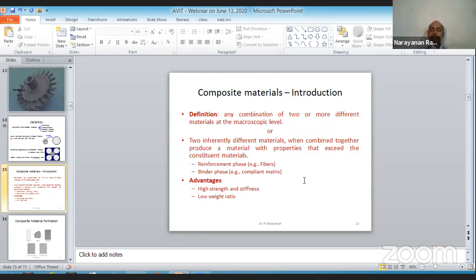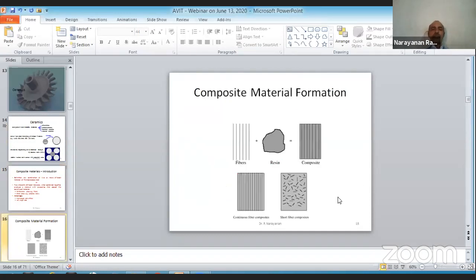We can have a polymer matrix, a continuous matrix of polymer, say polymethyl methacrylate, the bone cement, whose strength is generally low, and you can augment this strength by the use of, say, zirconium oxide or titanium oxide ceramic. Then you get a composite of titanium oxide particles or zirconium oxide particles in a compliant polymer matrix. This sort of composite is used in dental applications. So composites can be tailor made.